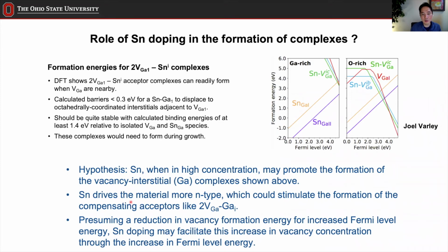Tin can drive the material more n-type because it's an n-type dopant. That can also stimulate the formation of compensating acceptors, such as the gallium vacancy or the complex itself. Presuming a reduction in vacancy formation energy for increased Fermi level energy, tin doping may facilitate this increase in vacancy concentration through an increase in Fermi level energy. In other words, if we increase the doping concentration, the tin doesn't have to go into the interstitial site by themselves. Even if they don't, it can perhaps increase the chance of gallium atoms, just the regular host gallium atoms, to jump into those interstitial sites.